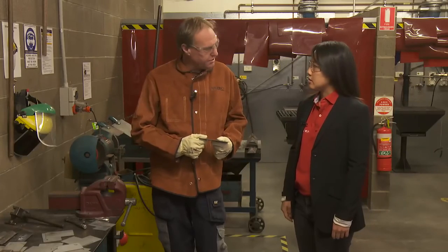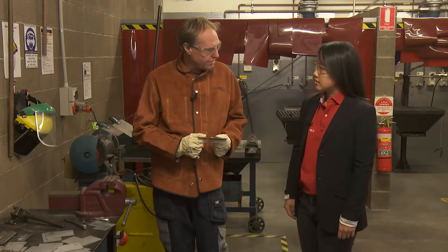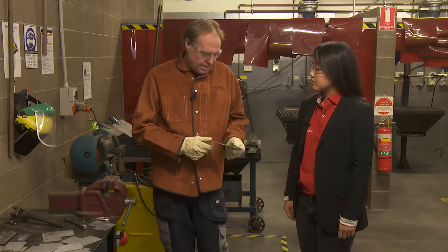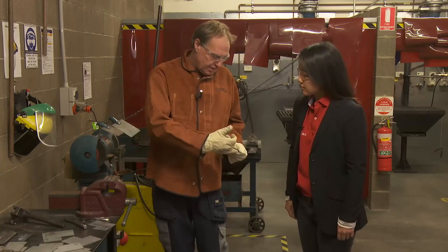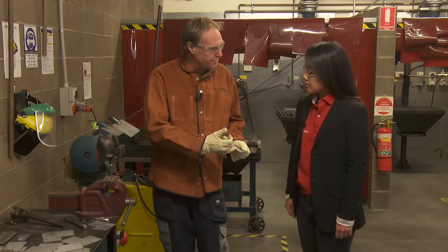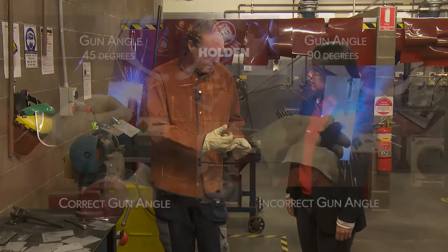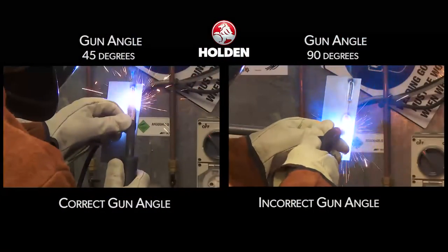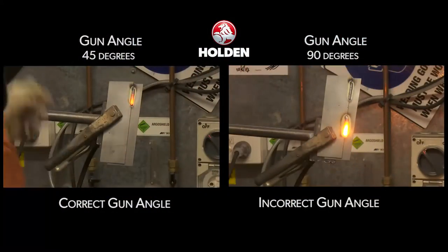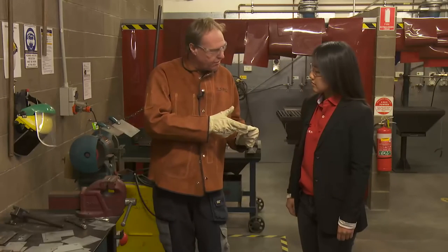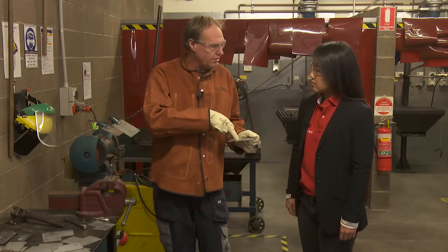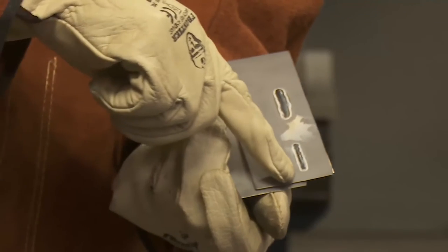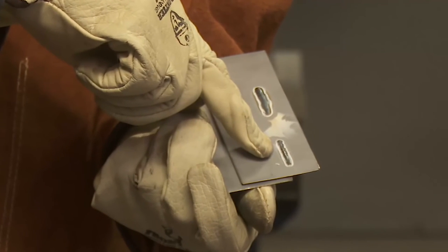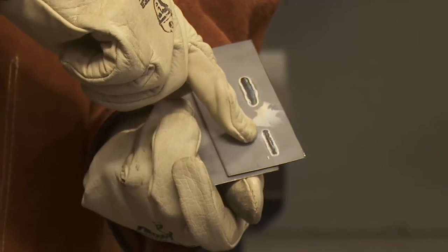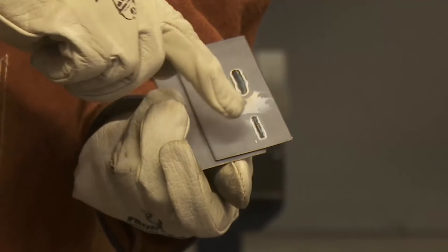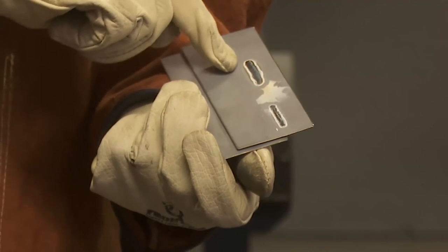I said I'd show you the difference between your gun angles as far as work and travel angles go. These two welds here, same settings, but they have different actual work angles. Same travel angle, they were both pulled down, but the work angle, that was on a 45 degree, and that was 90 degrees. You can see the different outcomes, along with heat affected zones. So that's what we're after, a very tight heat affected zone. That's an excessive heat affected zone.